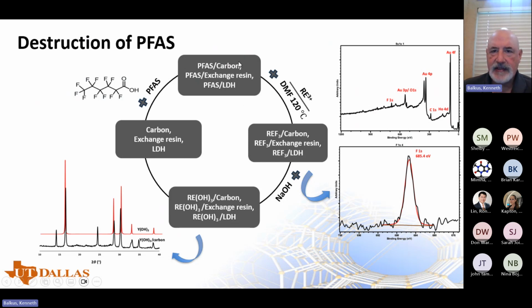So then what we do is, once it's adsorbed, we take the rare earth ions, like yttrium, for example, and we take this carbon and heat it up in DMF with the rare earth ions, and you can easily show that you make the metal fluoride. Okay, and the metal fluoride you clearly see by XPS, and of course you can see it by XRD. So now, to get a complete system here, we have to take this metal fluoride and regenerate our yttrium ions.